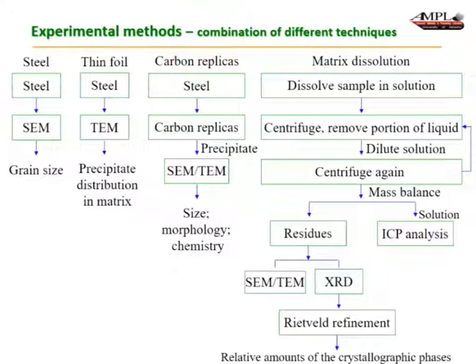So Jin Fang developed this matrix dissolution method where you dissolve the sample in HCl, and this could be anywhere between 10 and 60 grams of steel. You dissolve it, you then centrifuge, and you decant back and forth until you're left with essentially a solution that you analyze in the ICP. And then you're left with, on the other side, a residue where you can do the mass balance in terms of the original sample. This residue of precipitates you can look at with SEM, TEM, XRD, as well as Rietveld refinement.